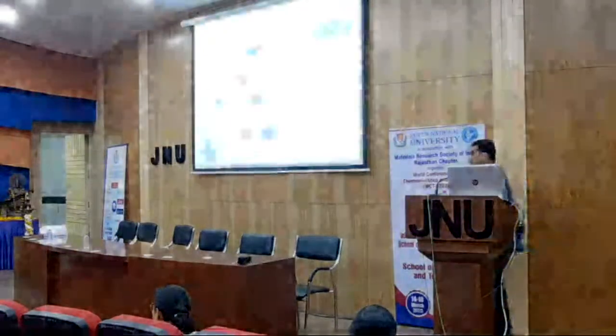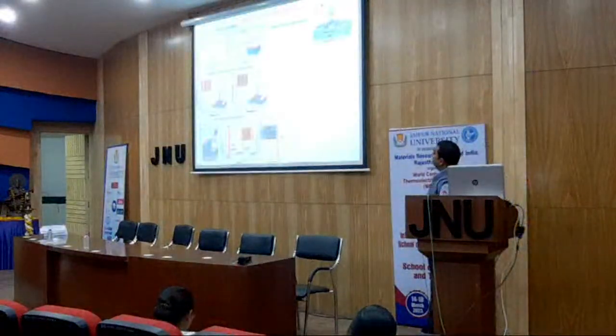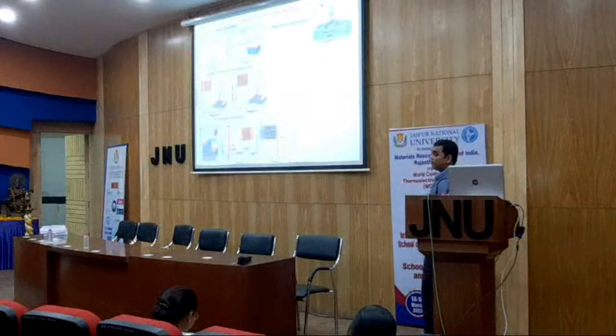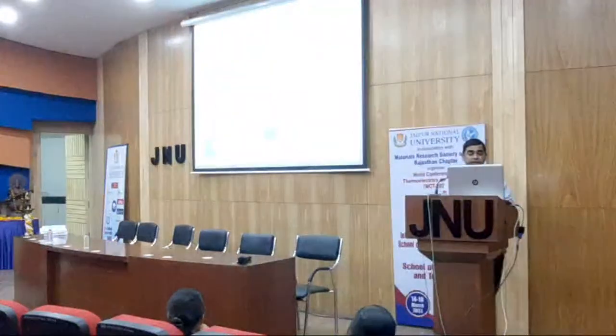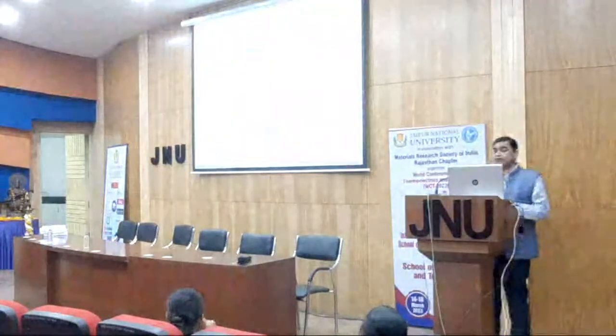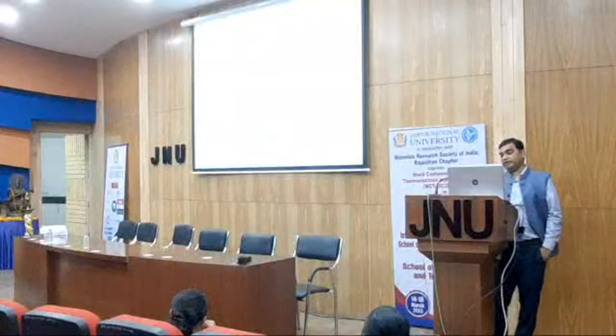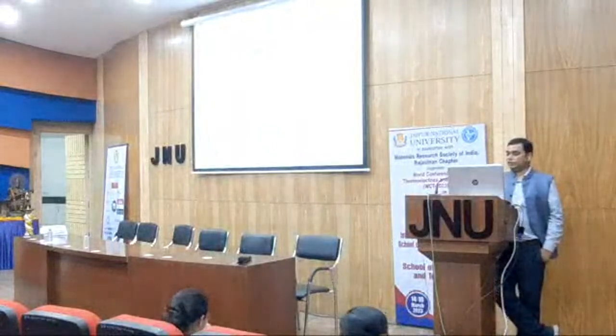Then another one is electrode engineering, because when you are growing, electrodes also have an important role, because their work function is playing a role. So we have studied the impact of these metal electrodes, and different metal electrodes are showing different behavior, and ultimately charge collection efficiency is observed to be higher in asymmetric electrodes like Pt/Ag or so.